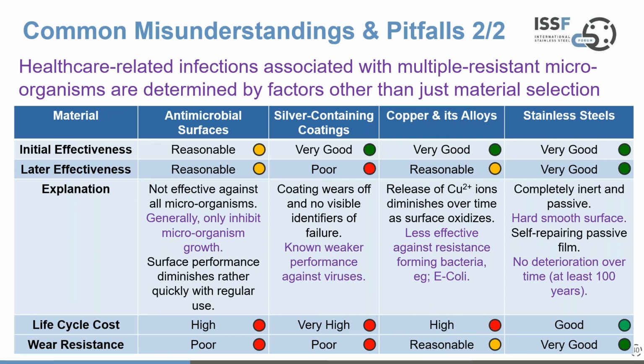Now, for these materials, if you look at their initial effectiveness, none of them are bad. Antimicrobial surfaces, because the performance is variable, would be classed maybe as reasonable. Everything else starts good. But then later effectiveness deteriorates for some of these products. Antimicrobial surfaces probably not, because they're not starting top of the pops, so to speak. But silver coatings become poor because they're softer and wear away, and copper fades to only reasonable because the release of copper ions diminishes over time, whereas stainless stays good all the time. Still remembering that you have to keep it clean.